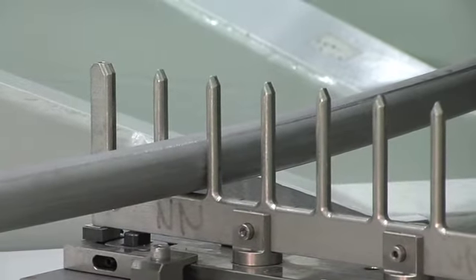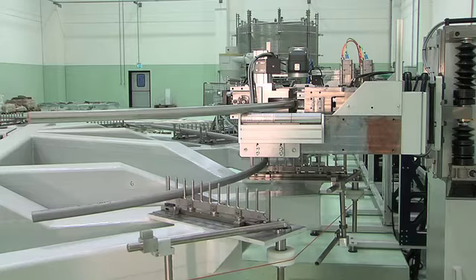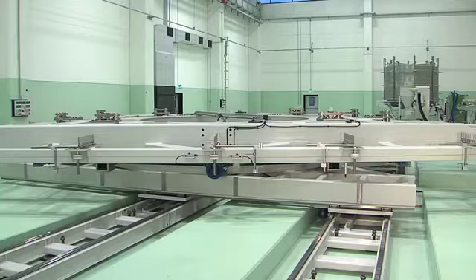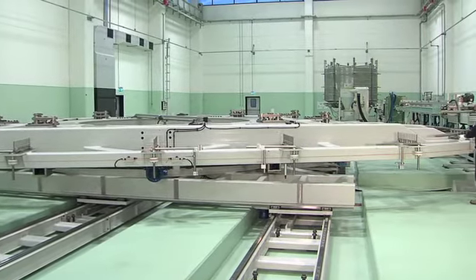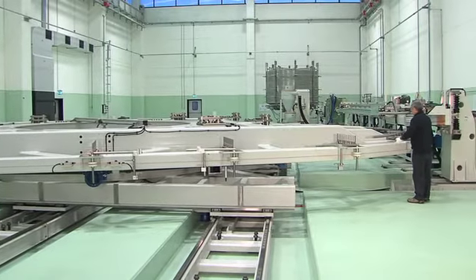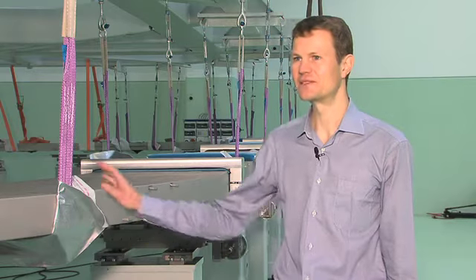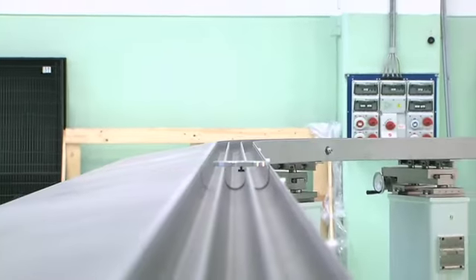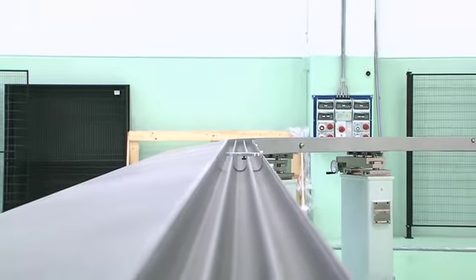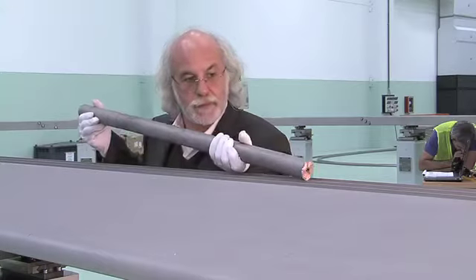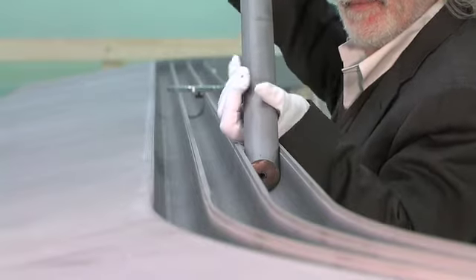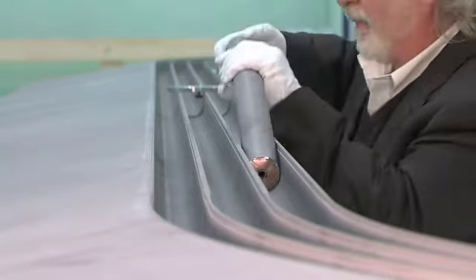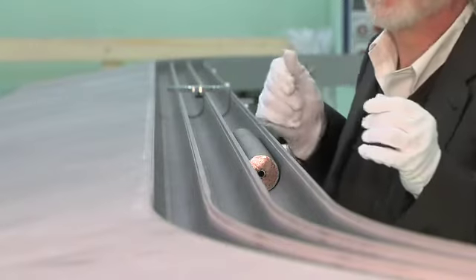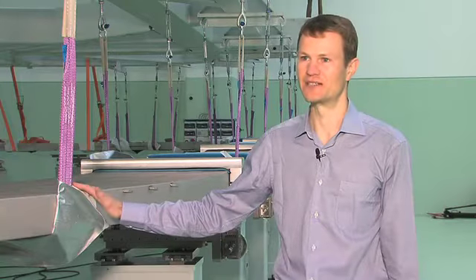In addition, there is a further change of length as a result of the heat treatment process, which we must also take into account. The requirement for high accuracy is linked to the fact that after the conductor is heat treated, it will need to be inserted into the grooves of the radial plate. The radial plate is similarly D-shaped. It's made of stainless steel and it has grooves on both sides to match the trajectory of the conductor. In order to fit the conductor into the grooves, we need to have both the conductor and groove trajectories match each other to within fractions of a millimeter.